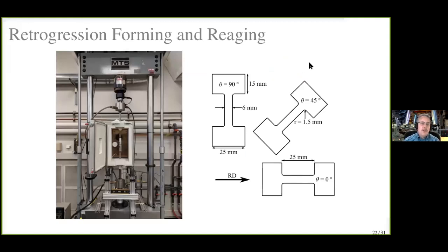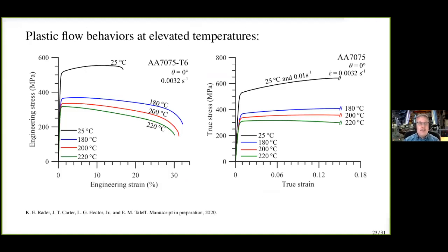Now, for retrogression forming and re-aging, we have to do tests at high temperature. So this is just an example of our high temperature setup. Box furnace, we do all our testing in here. And of course, one issue you deal with in sheet materials is they don't necessarily behave isotropically. So we took the rolling direction, and we tested specimens at 3 orientations: 90 degrees, 45 degrees, and 0 degrees to the sheet rolling direction. It ends up that our material is pretty isotropic. We have to do that all the time when we test sheet materials because this is not always going to be the case.